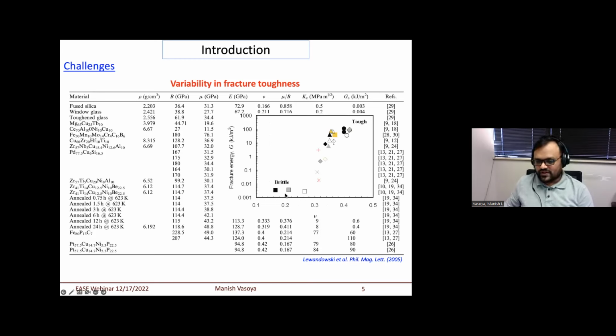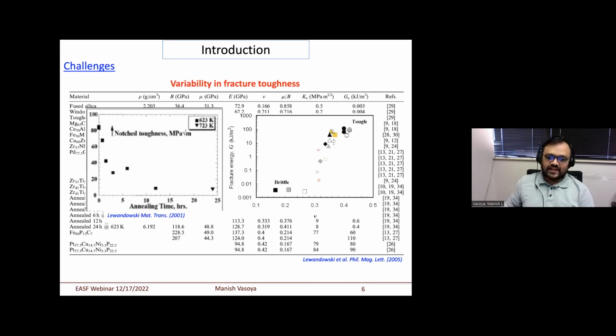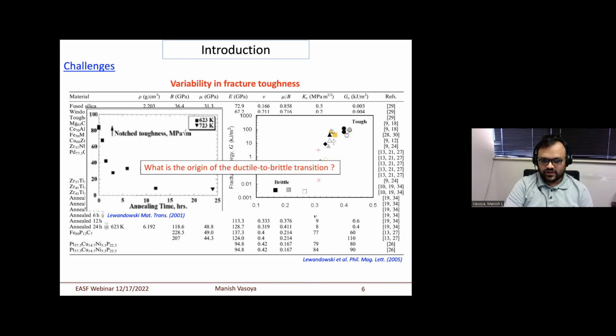For small Poisson ratio, you have a brittle material, and then if you increase the Poisson ratio due to some composition or microstructure effect, it gets tough. In a similar way, if you do very small annealing for a few hours, you have very high toughness. But if you anneal longer, though not that long, in the same order of magnitude of hours, you still have a variation of almost two orders of magnitude, from 100 to almost 10. So this is huge variability in the fracture toughness, and specifically the brittle to ductile transition is what we can show here. So the key question I'm addressing in this talk is: what is the origin of this ductile to brittle or brittle to ductile transition?